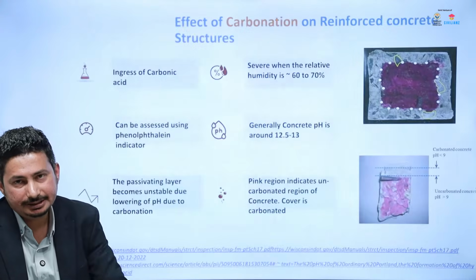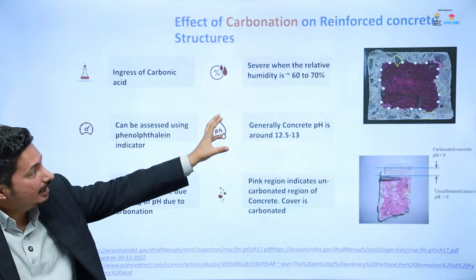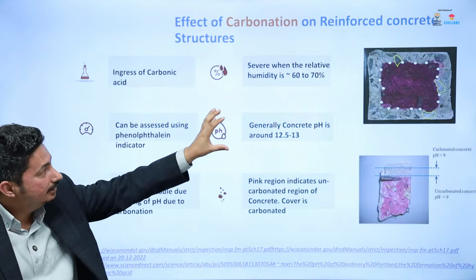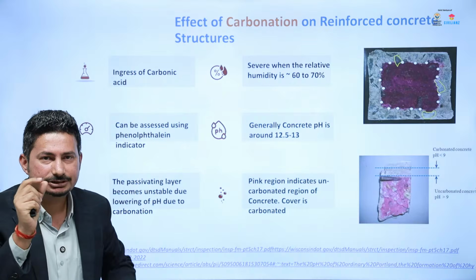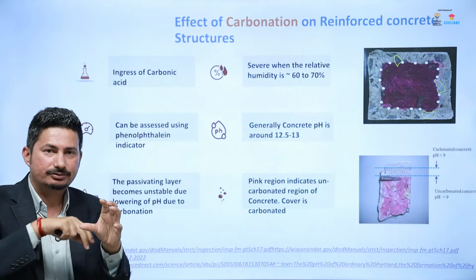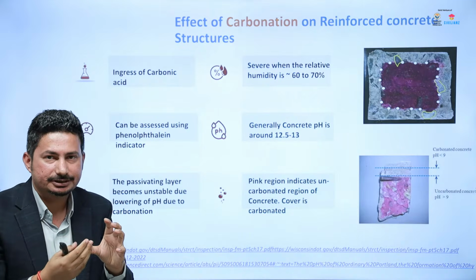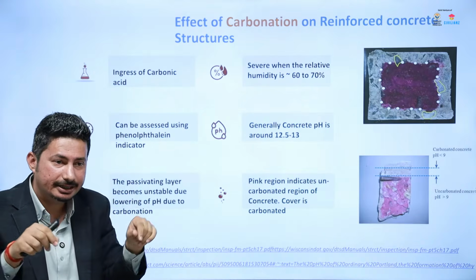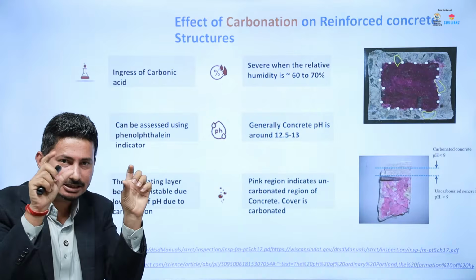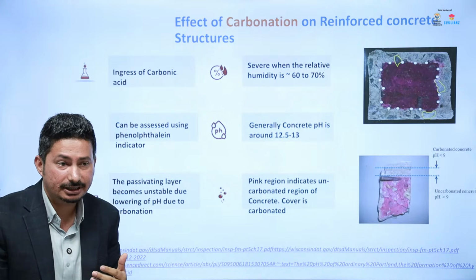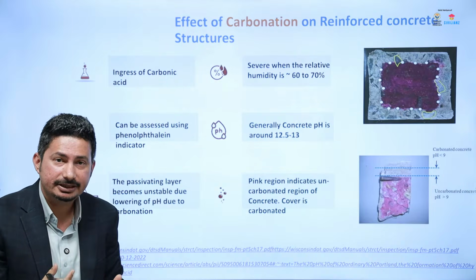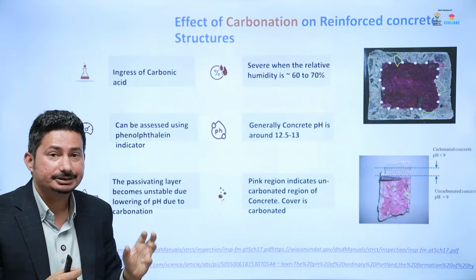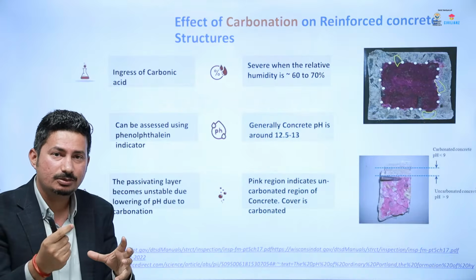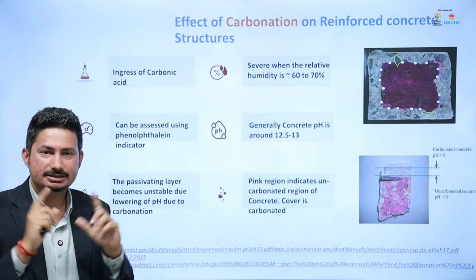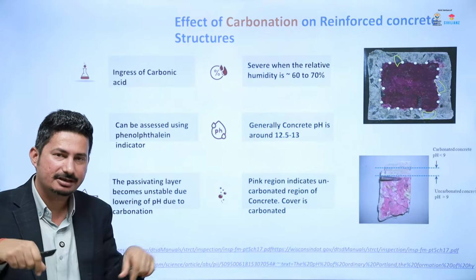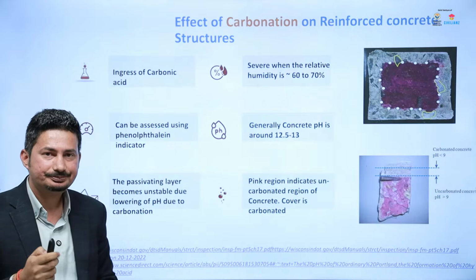Now, in the carbonation method, generally with the formation of carbonic acid, the top surface, every year, bit by bit, the carbonation of the concrete will happen, and mostly the first cover of the rebars will generally get affected because of the carbonation. This test is called the phenolphthalein test, in which the pink colored area you see is not carbonated yet, and the colorless area is already carbonated, and that happens with time in the concrete. Here the workmanship and the type of concrete that we are using play a very critical role in preventing carbonation. And to resolve that problem, we can use stainless steel rebars. Even if carbonation happens because of the circumstances where the project is located, this particular layer, the rebars, will not corrode by using stainless steel rebar.